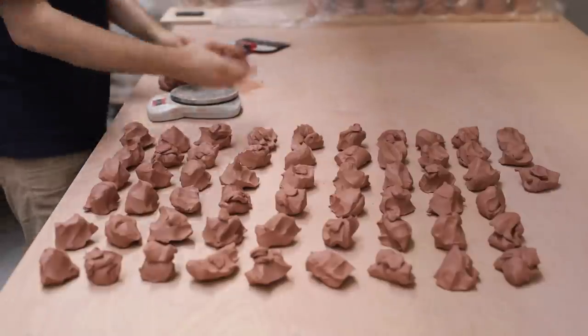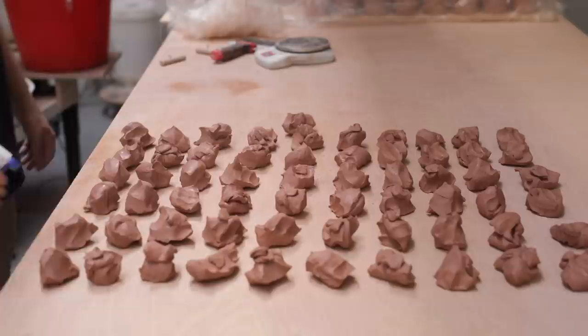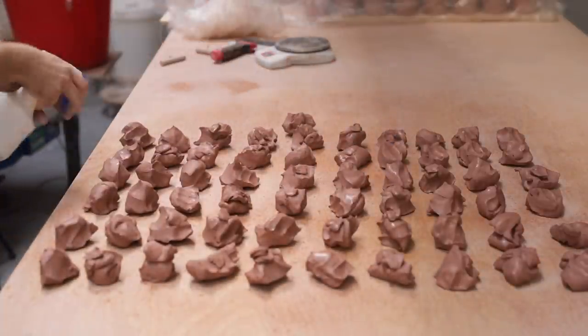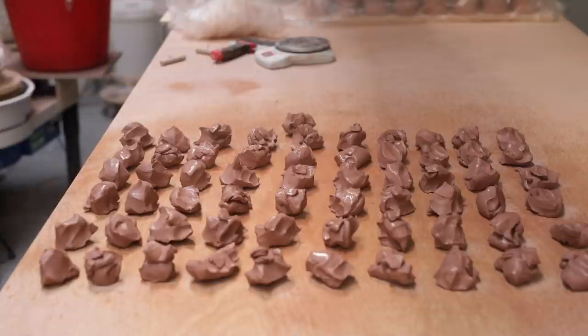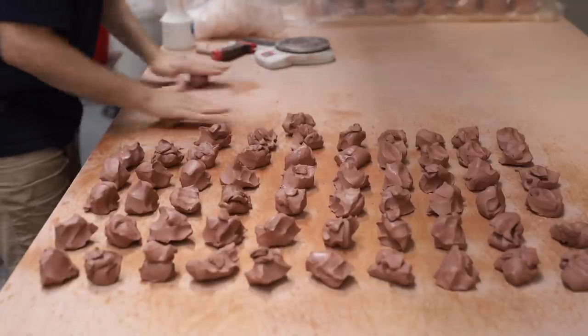At the time of filming this there was a small heatwave, and in my studio it's about 32 degrees Celsius. So to keep these lumps of clay from drying out, I made sure to give them a good spray with water, and as I was throwing I also kept them wrapped up in plastic, as otherwise they can quickly develop a sort of harder outer shell, which can just make centering and pulling the walls of clay up all the more troublesome.